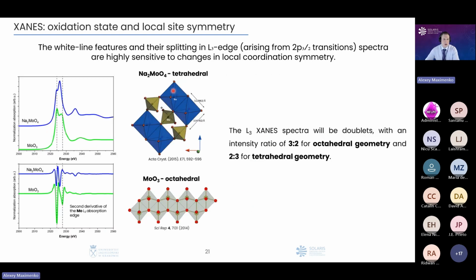Also, when we speak about the XANES region and different symmetries, we could see that the white lines, the most intensive point on the spectrum, for example here for the L-edge, could be split in two lines. Depending on the ratio between the first and second peak and the splitting distance between them, we could investigate what type of symmetry we have in our material, and also what level of distortion we have in our material.